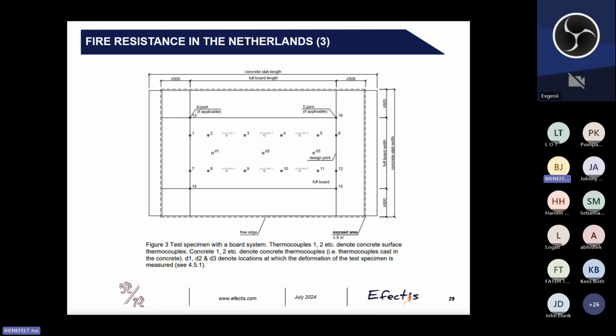What you also see in this picture is the instrumentation that's used. Behind the boards, in the concrete surface, thermocouples are installed to measure the concrete surface temperatures during the fire tests. But also thermocouples are installed at the joints and the special joints, the T-joints and the X joints. At the joints, the temperatures may be higher than behind the full board.